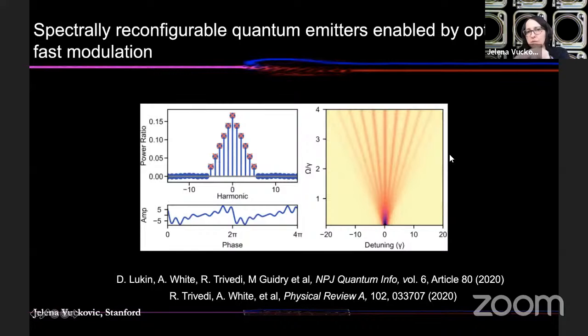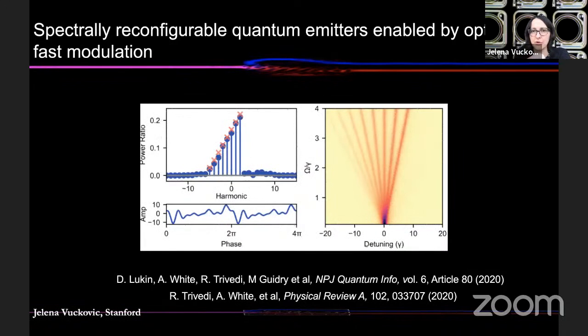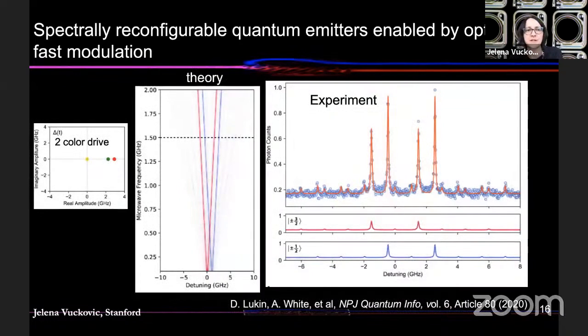And you can go beyond simple symmetric spectrum. You can actually produce something completely asymmetric by engineering harmonics in your microwave drive, which we find quite interesting, especially since we have a lot of inhomogeneities in the system, and then we can make these interesting spectra at the output that would overlap with each other. We've done that experimentally for color centers in silicon carbide.